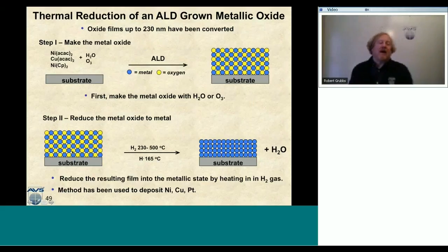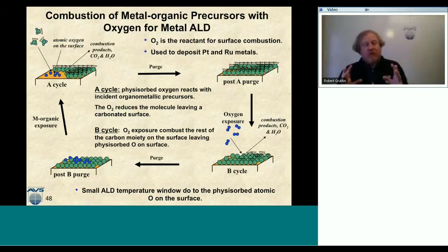And so if my reaction is too hot, the oxygen will not stay on the surface, and my reaction will shut down. So if the temperature is not warm enough, I won't actually undergo this oxidation step. So these particular chemistries have very small ALD windows, and it's primarily because we're relying on this physisorbed oxygen on the surface to actually drive the AB cycles. So I like that chemistry. It's very interesting, and you can put down platinum metal with it, which is remarkable.